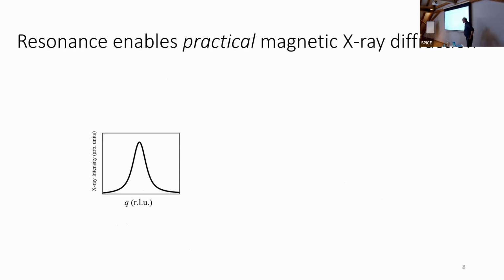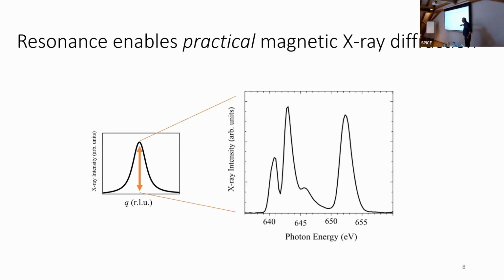So what do I mean by resonance? This is a magnetic diffraction peak. And when we cross an atomic resonance, its intensity goes from being like nothing to being very intense and then back down to 0. And of course, more is encoded than just more intensity in this. This is the manganese L2 and L3 edges, of course.